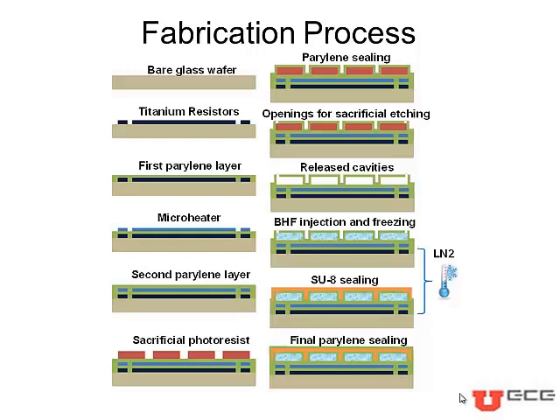Next, we fabricate the hollow cavities of the reservoir by sacrificial etch technique using 16 micron thick layer of photoresist as a sacrificial layer. Next, we fabricate the top wall of the reservoir by depositing a 5 micron thick layer of parylene. Holes are etched on the top wall to the spacer layer by oxygen plasma, and then the entire device is dipped in acetone overnight to remove all the spacer, leaving behind the hollow cavities. Next, the cavities are filled with a dilute solution of buffered hydrofluoric acid and subsequently sealed.